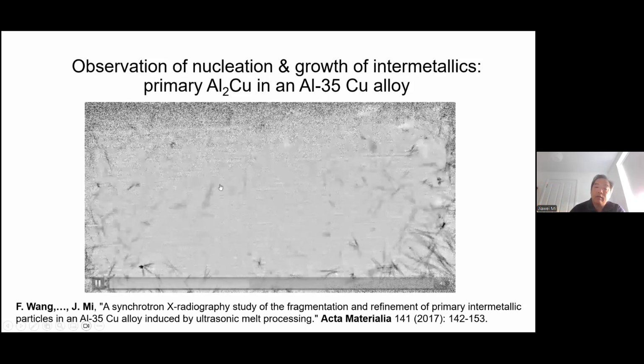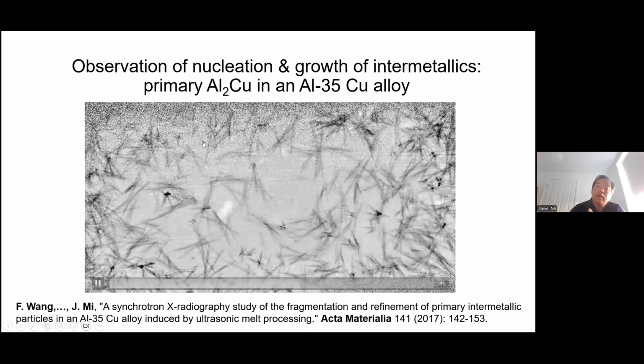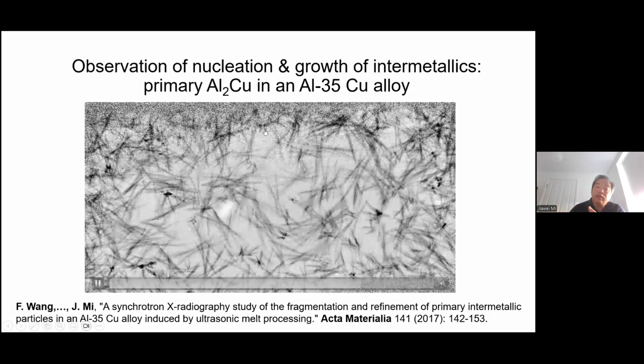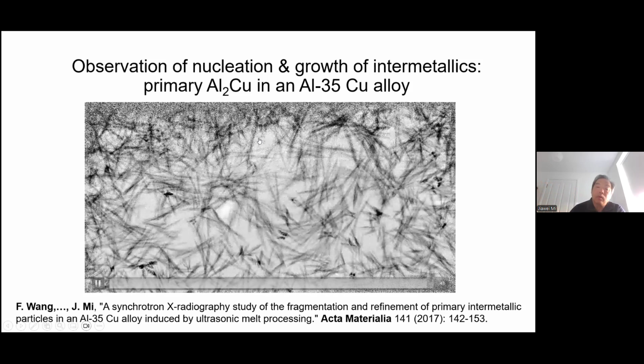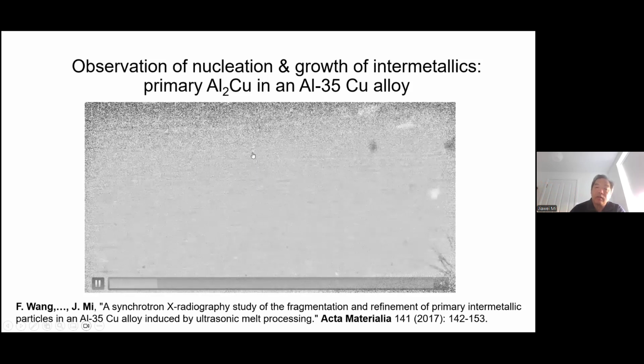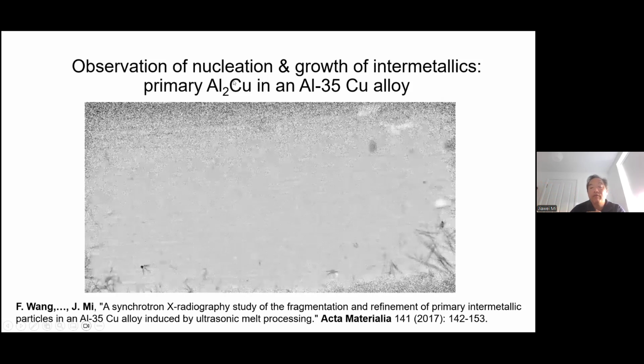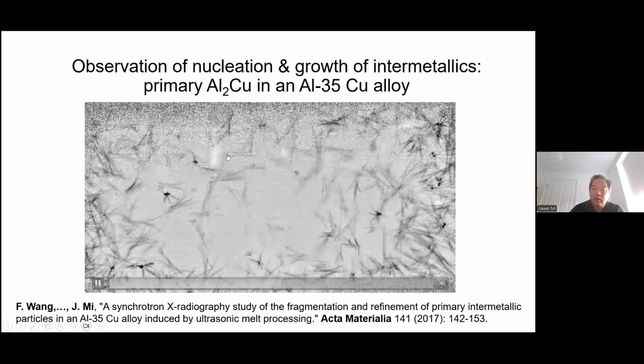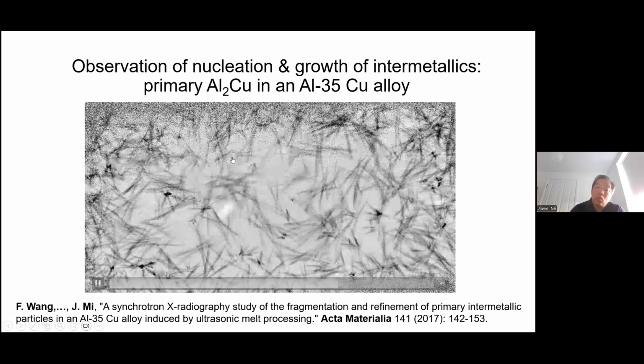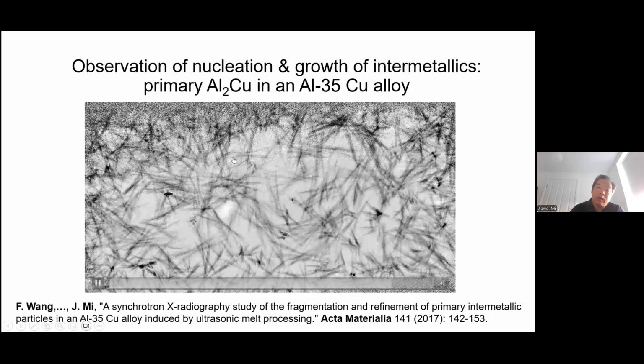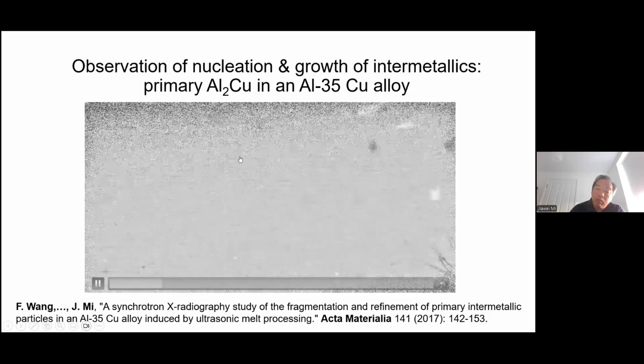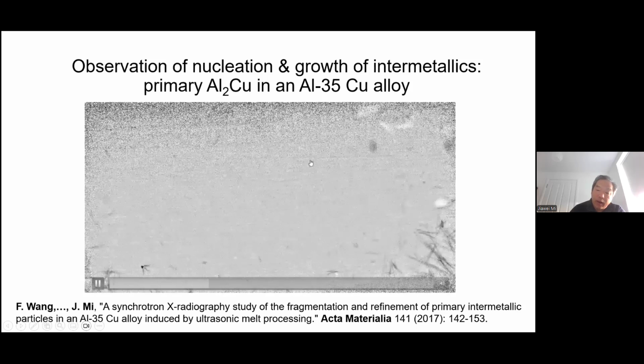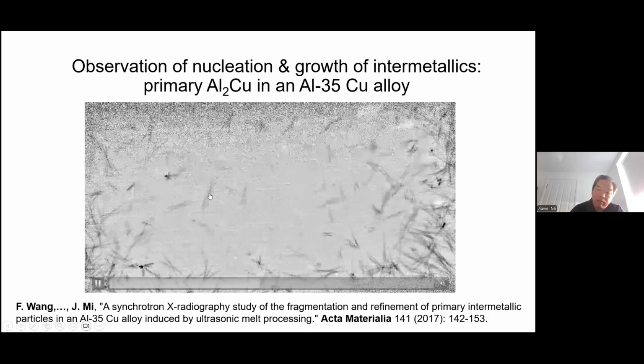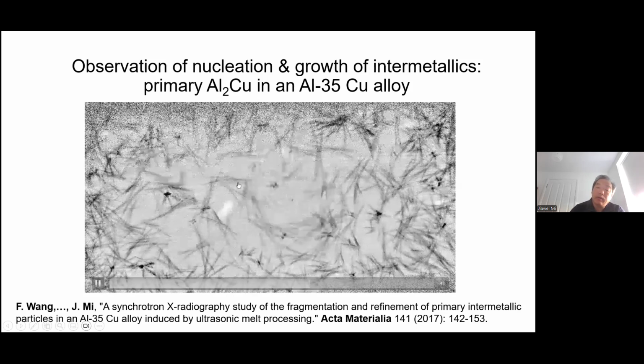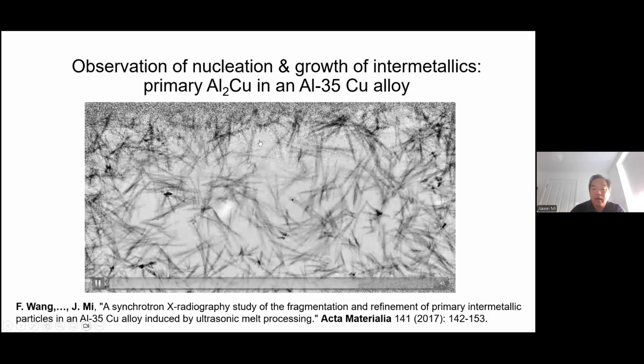This is one case already solidified. And when it's cooling down, you just look at which phase is growing. And this is a particular aluminum-copper phase. And we are watching this with and without the application of ultrasound. But what we are more interested in here is, just before any phase comes out, the black one, how does the liquid structure evolve to form that kind of thing?